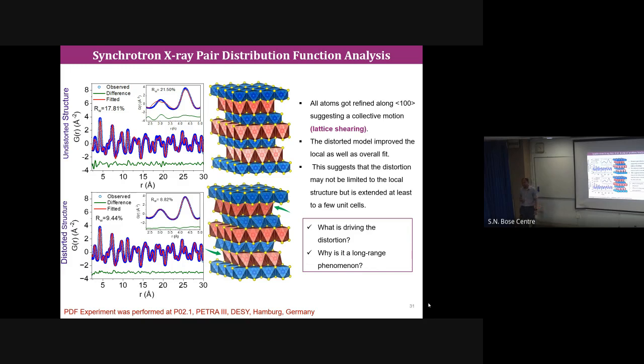So why is it like that, right? Although the structure is derived from bismuth selenide, the van der Waals gap compound, we are forcefully closing the van der Waals gap, but this compound does not like it. So it tries to open up a little bit of the gap by shearing the layer. That's what we got from the PDF data, and that explains both global structure and local structure. What is the distance? The interlayer distance. See, here it's much lower than a van der Waals gap. The thallium selenium distance is slightly higher than the covalent bond distance. Whereas in bismuth selenide you have a van der Waals distance around 4 angstrom, here it is around 3.19, exactly, the second decimal. It's slightly higher than the covalent bond.